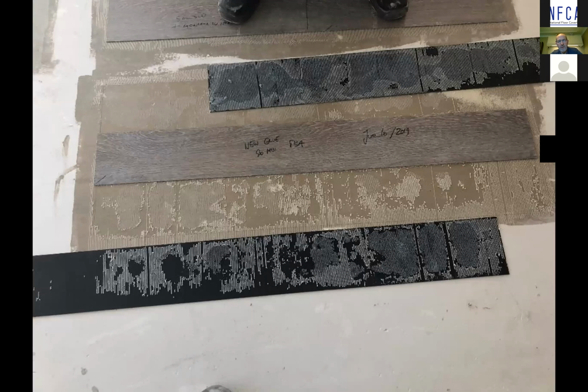And so what we did here was we went to a polyurethane primer. So a polyurethane primer is quite a bit different than a water-based. It's more of a resin-based, and it's a deep penetrating type of primer that can go in and strengthen and solidify the surface. And when you're doing these bond tests, you need about 3 days.